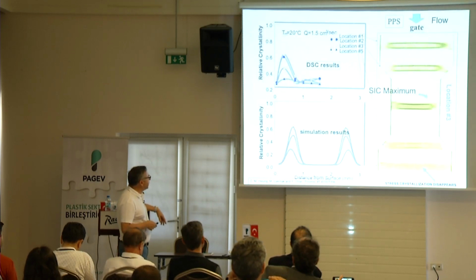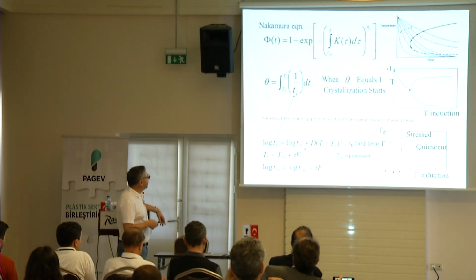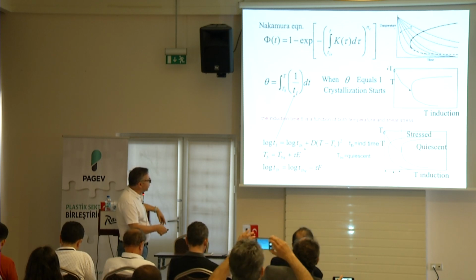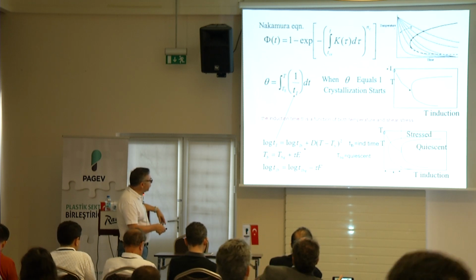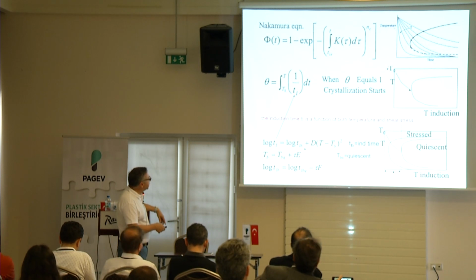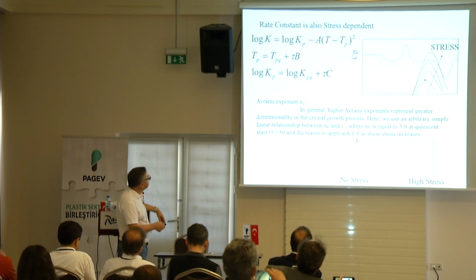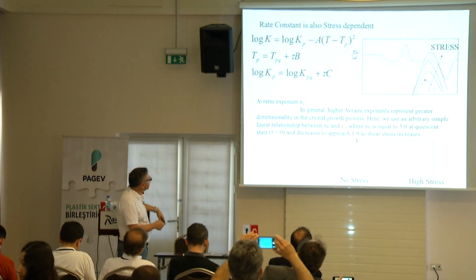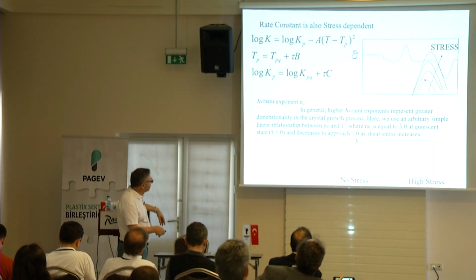But essentially what we did was very simple. What I told you, the effect of the stress on this continuous cooling diagram, is put into an equation that connects the stress to the movement of this curve. And secondarily, the rate constant is also controlled by the stress. That's also put into a functional form, as well as the Avrami exponent. They put it together into a model.